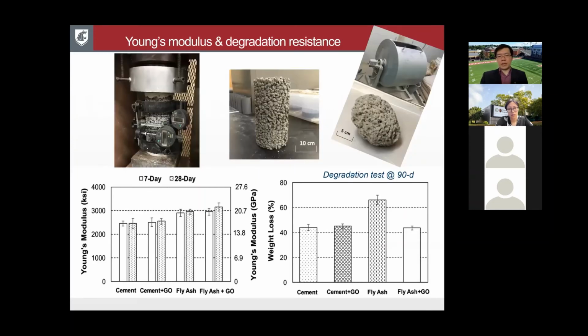Now, what about Young's modulus and abrasion resistance? Again, on the left-hand side, at the bottom, you see the Young's modulus of the geopolymer ones are significantly higher, but still reasonable in terms of comparing against cement pervious concrete. Now, the degradation or the abrasion resistance through the degradation test at 90 days shows that you basically need the graphene oxide to make this geopolymer pervious concrete to be as good as the cement ones when it comes to abrasion resistance.